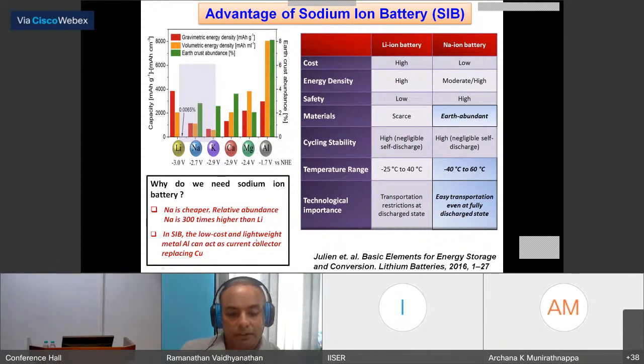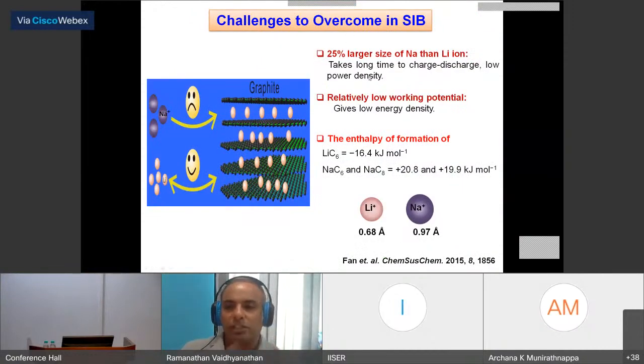And also, sodium-based batteries will increase the weight because lithium is lighter than sodium. But at the same time, if you can use aluminum as the current collector over copper, which is much lighter, you can balance the weight that sodium brings in, to some extent, so that you can keep the weight in check. And then there are two major problems with sodium ion batteries. One is that people simply say the larger size of sodium is the problem, and that is absolutely a problem, because the larger size does not let graphite be used as the anode material. What you will have is a volume expansion, because of which graphite can give a lot of trouble when you use it as an anode.